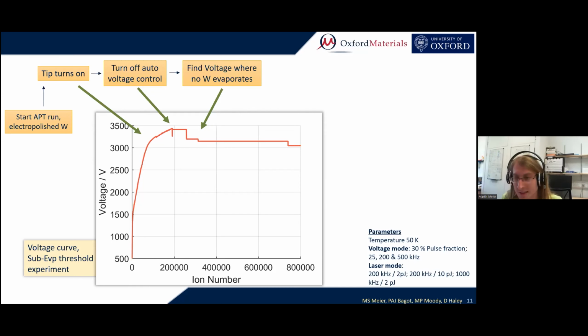And we know the point in time when the evaporation has stopped by just looking at the spectrum. Once there are no tungsten peaks left, then we know there's nothing evaporating out of the tip anymore. But we do still see hydrogen peaks.